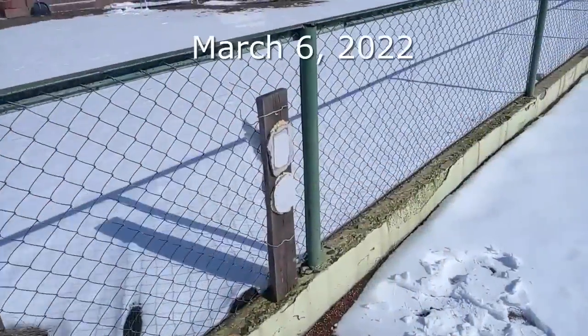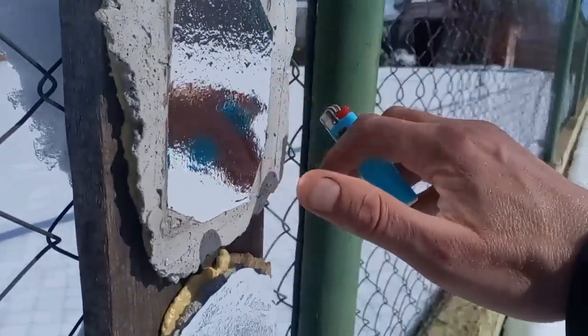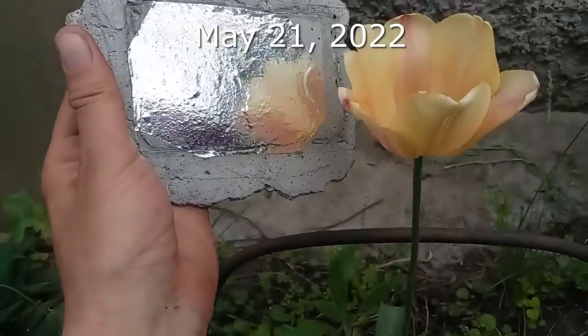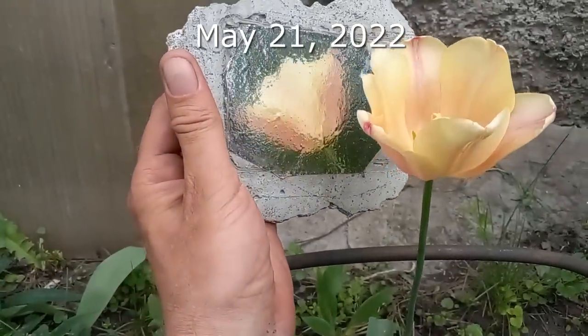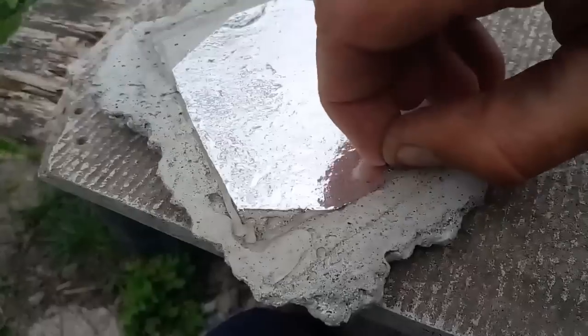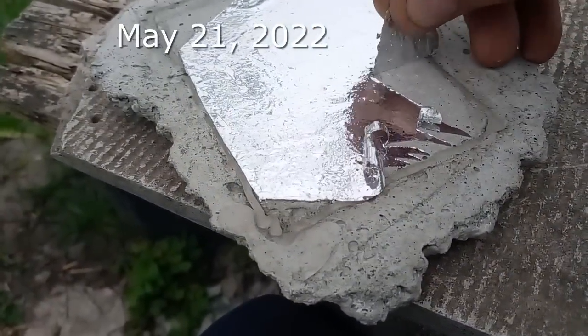Nevertheless, a few months ago I used that cheap glue to fix this piece of film to concrete, and then it was tested outdoors under snow, frost, and rain. After 3 months, that glue continues to hold the film, and we can notice that it holds it quite securely.